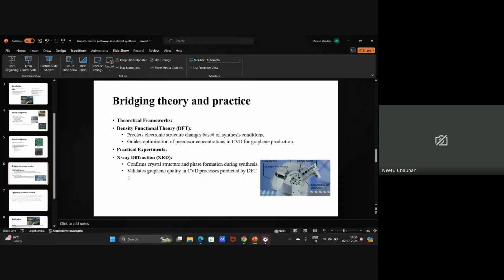If we talk about this bridging theory and practice through an example, then using density functional theory, researchers predicted the optimal conditions for synthesizing graphene via CVD. Practical experiments confirmed the theoretical predictions, leading to the production of high quality graphene sheets with controlled thickness and electrical conductivity.